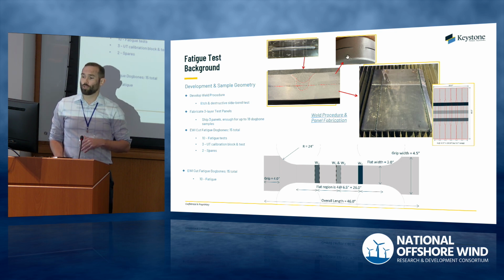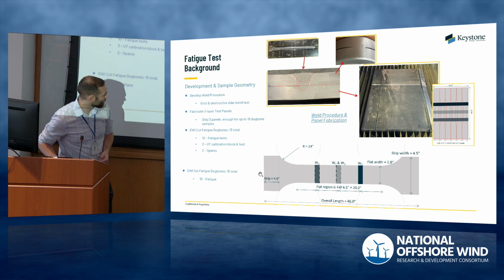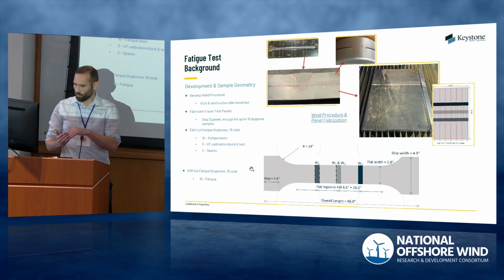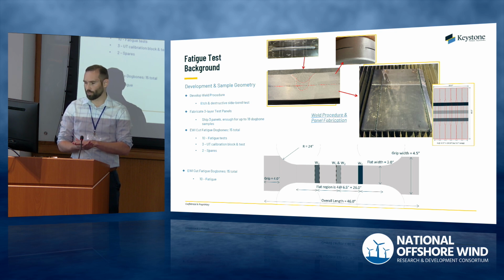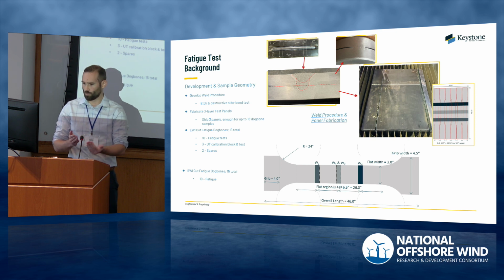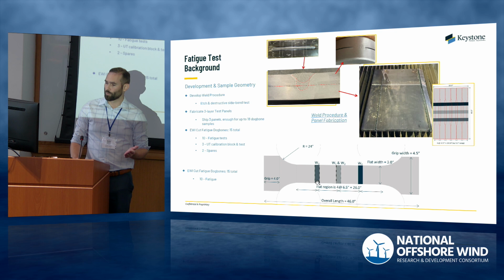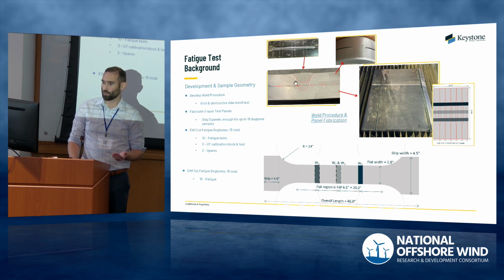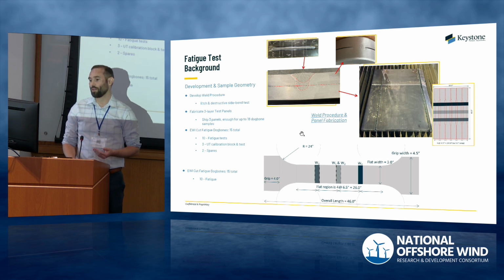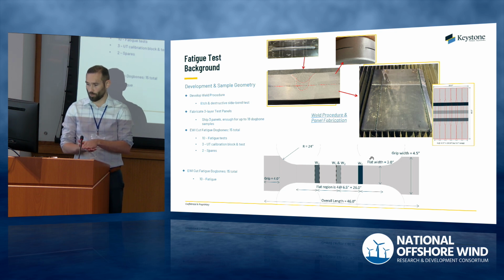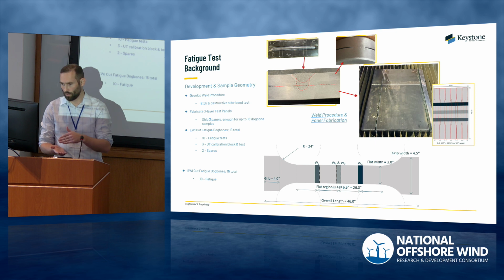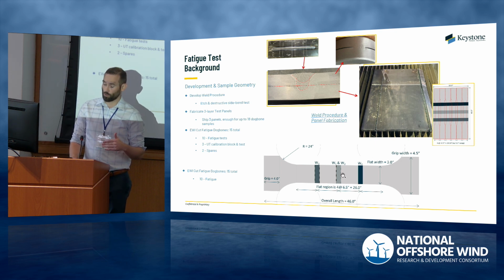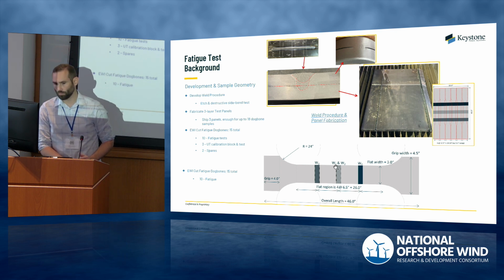So after we developed that weld, we did some destructive testing. We saw ductile behavior at the notches of the weld, and then produced panels from which we would cut dog bone samples. And here are the details of the dog bone sample. So the middle weld is actually a double-sided weld, just like our conventional tower would be. And so that's weld number 1 and 2. We offset from that a weld just like this. So it's welding into the bottom layer as backer, and offset the other direction and welded a fourth time by welding that third layer into the backer. So each one of these samples actually has 3 welds that are being tested, one of which is a double-sided weld.